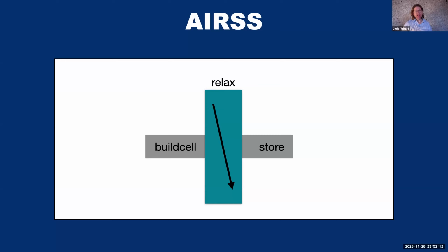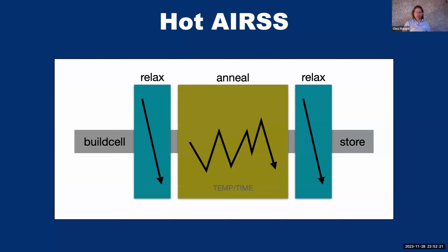Now, because we have these possibly hundreds of thousands of times faster potentials, we can do things we wouldn't have dreamt of doing before. So now we've been introducing the idea of what's known as Hot AIRSS, where instead of just relaxing the structure, we build a structure, we relax it, and then we can do a long, possibly half a nanosecond or multiple picosecond anneal at a given temperature, and then we relax the structure again and store it.